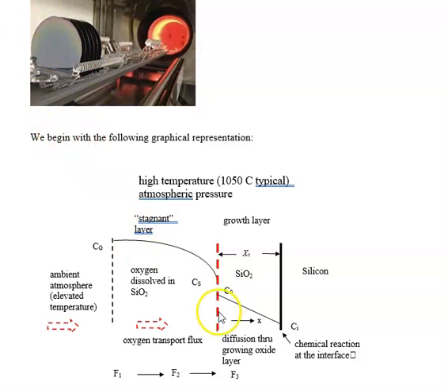So there's a couple of really important constants, namely how much oxygen can we cause to dissolve in the SiO2 layer. The oxygen's got to get into here. Here it exists as a gas. Here it exists as a solid. So we have a gas-solid interface, and the law which governs that is called Henry's law, and we'll talk about that a little bit later on, but just as a preview, it says that the higher the concentration of oxygen in the gaseous stage, the more I can push in to the solid stage. And that makes sense. And we'll see an animation of that.